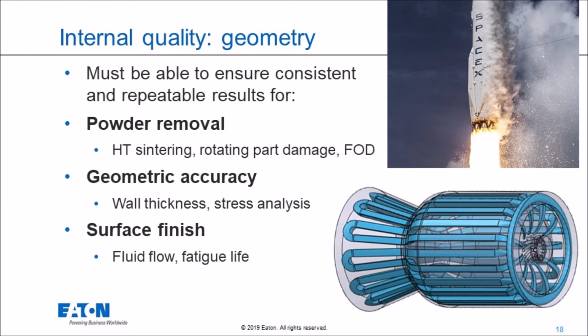How do you ensure geometric accuracy, so that the wall thickness you've put through your finite element analysis and stress analysis is actually accurate, and that the wall is not too thin? And how do you ensure that the surface finish in these internal passages is good? We know the surface finish changes depending on the angle at which you build it, and that's going to affect both the fluid flow and the fatigue life of that part.